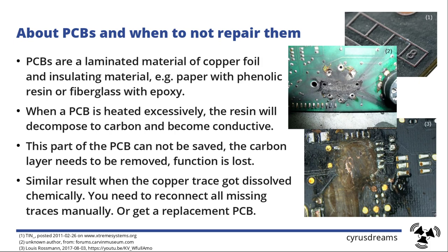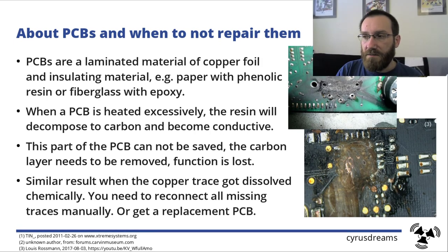That one is a snapshot from a video from Louis Rossmann. I really highly recommend that. The link to that is down in the description, where he goes to the trouble to remove from that failed MacBook the Thunderbolt connector and its circuit. And what he had to do is scrape off all the carbonized material. You see that here, he removed everything completely down to the first inner layers that were unaffected. And you never will have a Thunderbolt on that board again. And even for something vintage, that might mean that one of the serial ports will never be working again, or you need a separate PCB that replaces that function, or get a replacement PCB for the whole board that is damaged like this. That might be one of the limits of repairing.